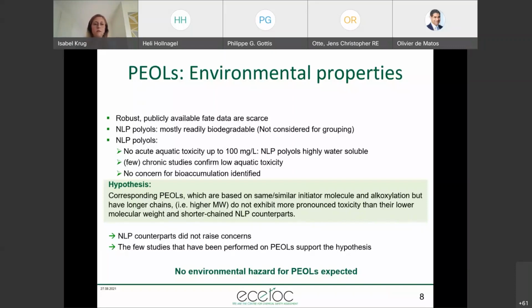Again, our hypothesis also applies here, namely that it is not expected that the corresponding PEOLs, which are based on the same initiator molecules and alkoxylation, but have a higher molecular weight, exhibit more pronounced toxicity than their lower molecular weight and shorter chained NLP counterparts. The data for the NLP counterparts did not raise any concerns, and the few studies that we do have for the PEOLs support this hypothesis. So in summary, we conclude that no environmental hazard for PEOLs is expected.